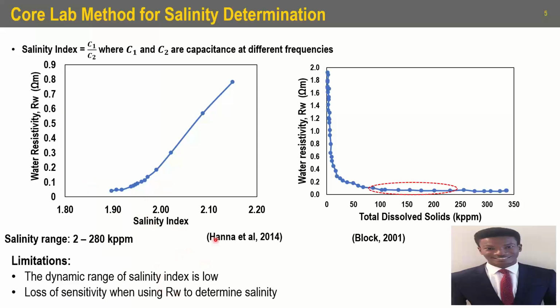Another limitation we have is that by looking at this chart on the right, we see that if we want to infer salinity directly from water resistivity, there is a point at which we lose sensitivity in determining salinity just from water resistivity at around 100,000 ppm. We see that it pretty much flattens out. So this is another limitation that this method presents in determining salinity from the water resistivity.